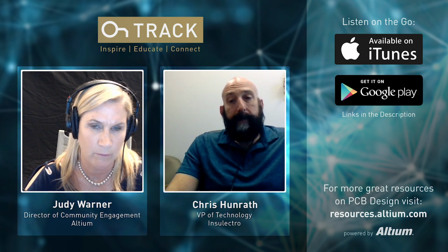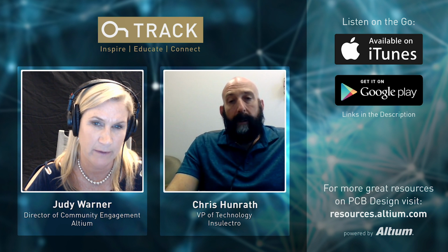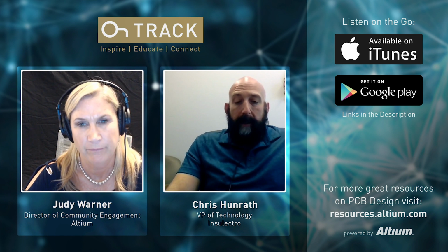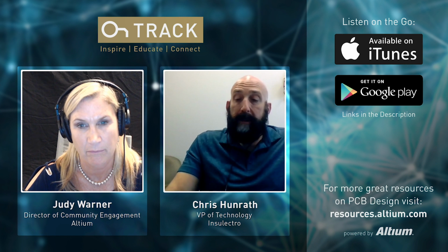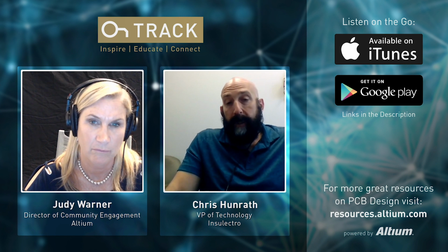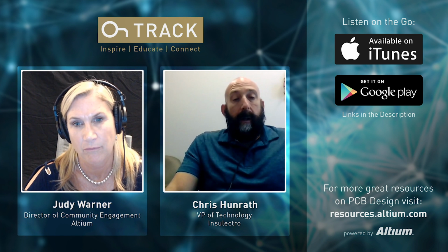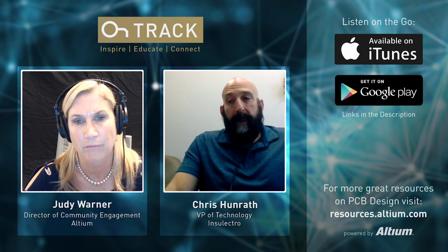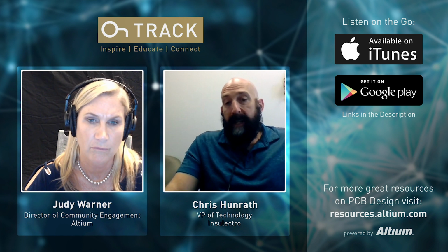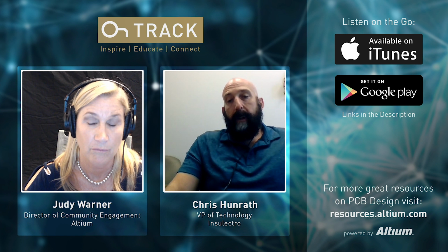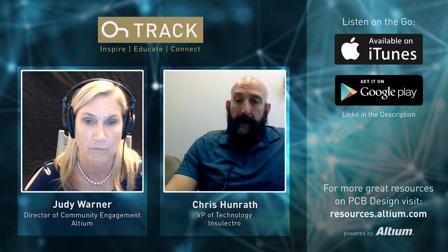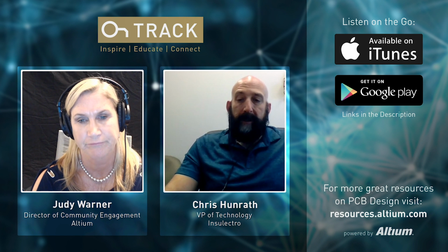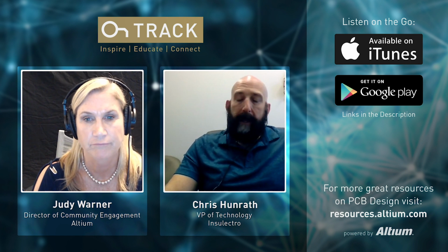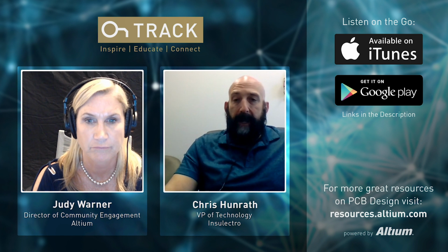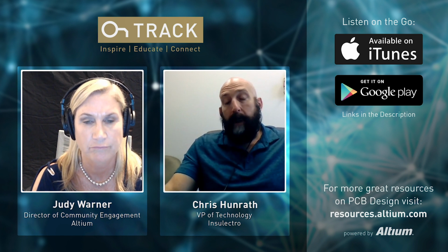So if you're a designer, what kind of design considerations do you need to make up front? Okay, so my recommendation would be to think about the design, think where it would make sense to split up the layers and provide the most design benefit. Generally speaking, we like the via to have a 1-to-1 or less aspect ratio. Now that might sound restrictive, but it's only in that one B stage layer. Oh, okay. So that's an important consideration. So in other words, if I have 5 mils of B stage, I would want my via to be 5 mils or larger where I'm going to apply the paste. That has to do more with the paste physics and how it fills the via.